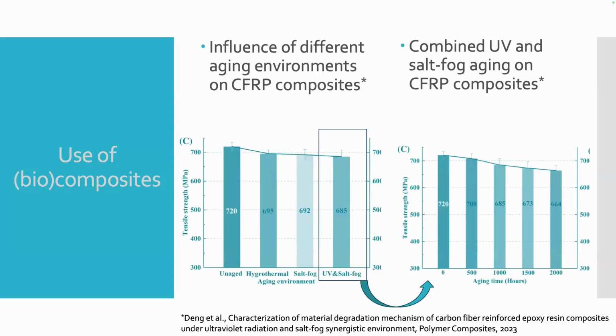This is the study done by Deng and his team that was published last year, and they studied the influence of different aging environments on carbon fiber composites. And what they concluded in their research is that the most severe influence on the mechanical properties, on the strength of the composites, has the combined effect of salt fog and the ultraviolet lighting. They even performed the aging over 500 up to 2000 hours and saw how well they behave.